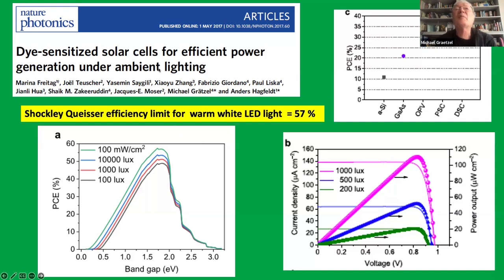When we talk about ambient light, like now when I look outside, we have a cloudy sky, then the energetics of energy conversion are different, because there's no or very little infrared radiation in the diffuse light. And so the Shockley-Queisser limit, which is the optimum band gap of your absorber, shifts to the blue. This is particularly true for LEDs, for light emitting diodes that are used as indoor lighting. And so instead of having 32% solar to electric conversion efficiency, with this kind of diffuse light we get much higher efficiencies, for example over 50%. And so that's a real worthwhile source to recapture indoor or diffuse light and convert it back to electricity.